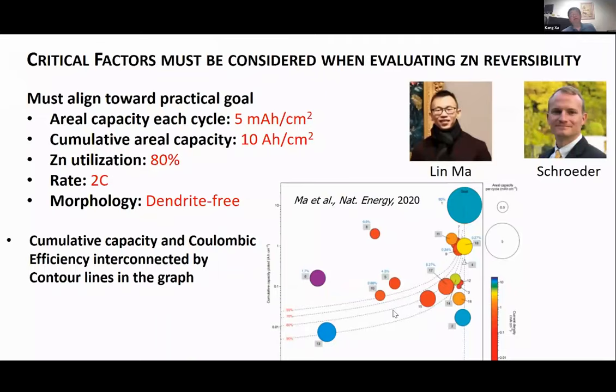They represent how much capacity retention you have if you want to reach a certain amount of cumulative capacity under each given coulombic efficiency. Of course, the most ideal case here is 100%, which gives you a straight line. It gives you an infinite number of cycles, which can only be approached but never realized in real life.